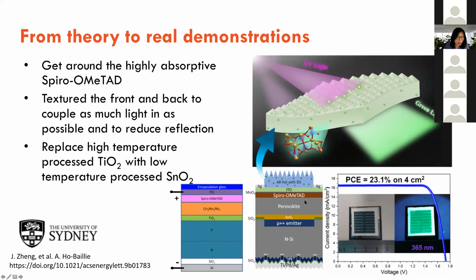Also, to improve the light management of the cell, we decided to texture the PDMS layer and also texture the back. So when we texture the surface of the solar cell, it allows the sunlight to be coupled into the cell instead of being reflected. So, you know, if you have a flat mirror image, you will get quite a lot of sunlight being reflected. So you look at the cell, it looks like a mirror. Whereas if you texture it, you will get as much light into the cell and get it to bounce around as well. So when you have light being bounced around the solar cell, it increases the chance of the light being absorbed.